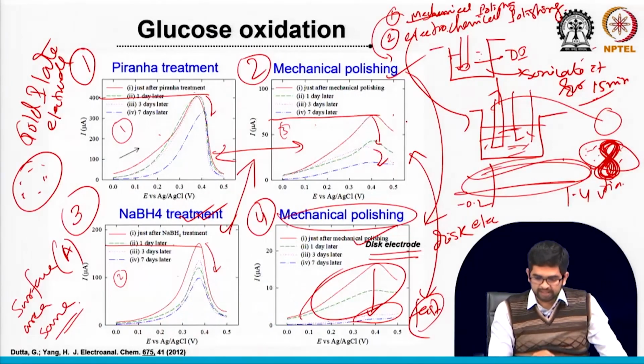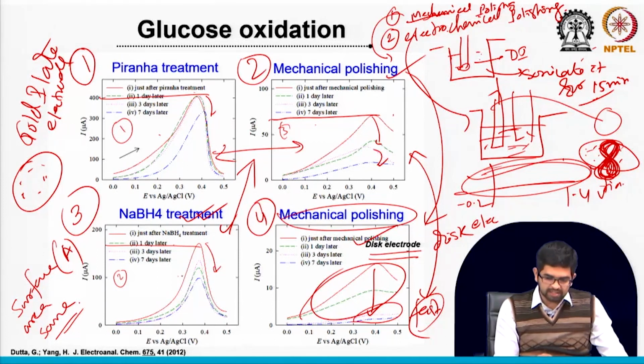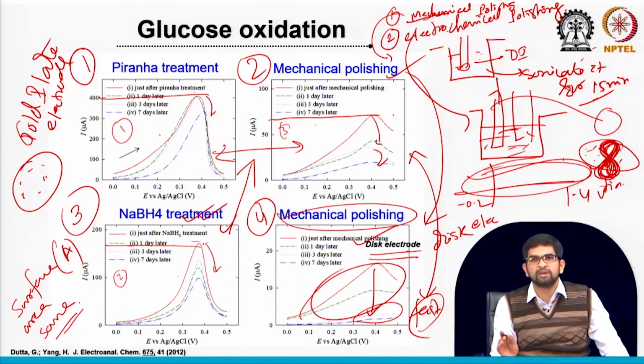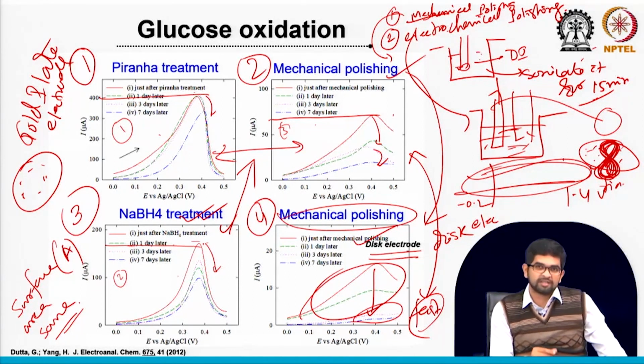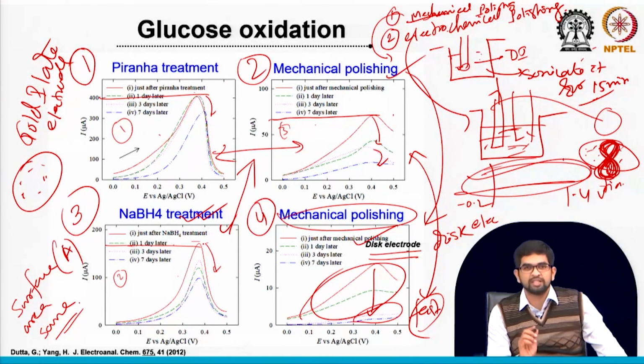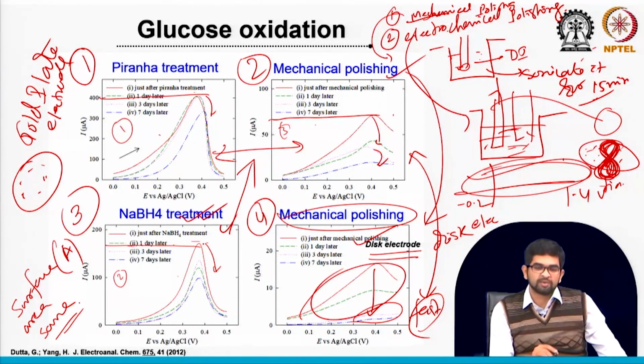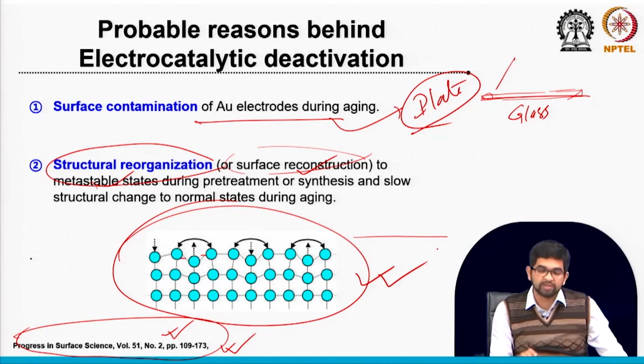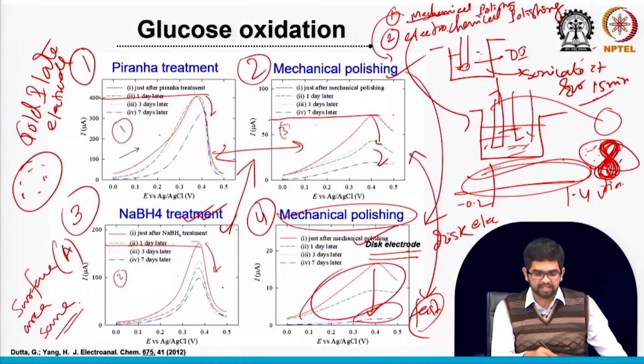So let us go back to the sodium borohydride treatment case. In this case, we can see the enhancement here, but this enhancement is not due to the cleaning of the contaminant. This is maybe due to the surface reconstruction. That is why I am saying the reason for this activation change is not only carbon contamination removal, but also surface reconstruction or surface reorganization, this factor. That is why we assume this factor. In the sodium borohydride case, we can say that although the surface is not that clean after the sodium borohydride treatment, still we can see the enhancement.